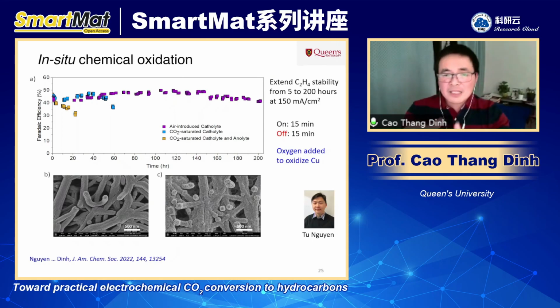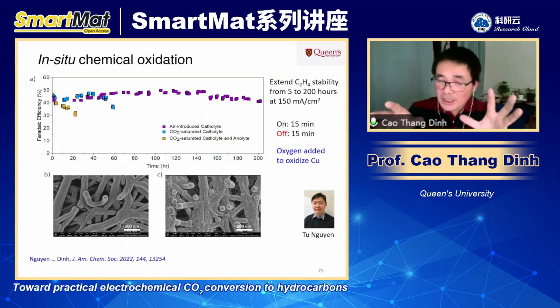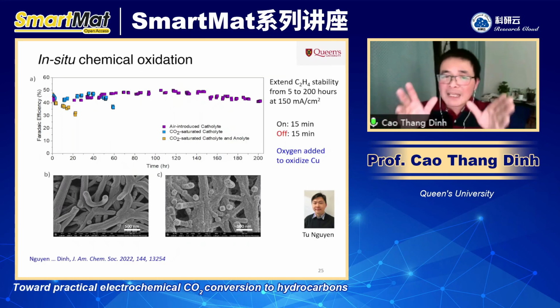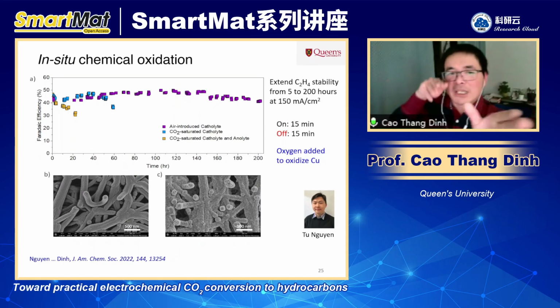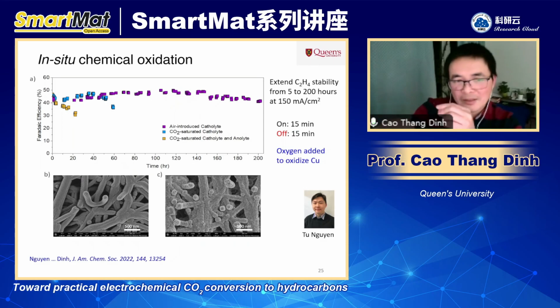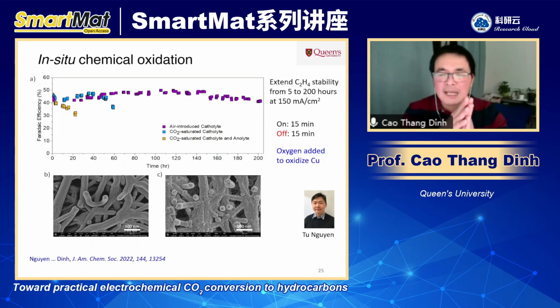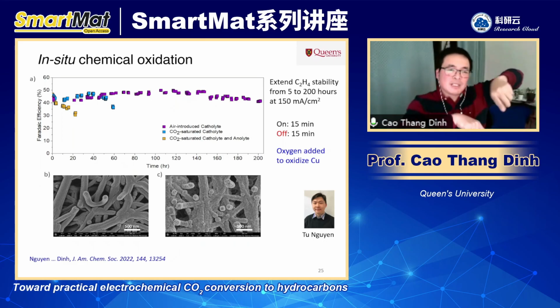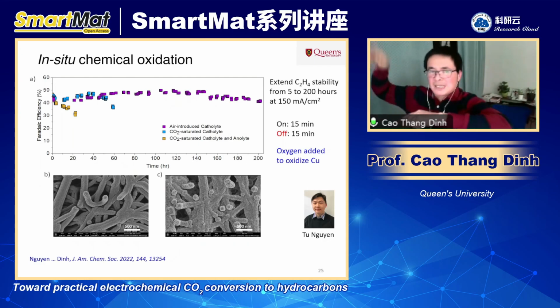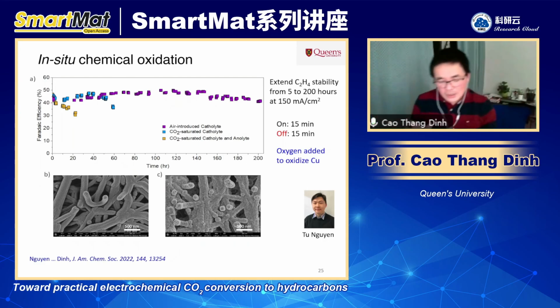So what we did in this work, with my postdoc visiting scientist, is that we use oxygen to oxidize the surface, right? We do not apply the positive current to oxidize the surface, but instead we turn off the system and introduce the oxygen to the cathode. So that oxygen is going to oxidize the surface of the copper, turn it into copper oxide. And then we run the reaction again after 15 minutes, right? So you run the reaction for 15 minutes, you turn it off for 15 minutes, and then you run it again. Just keep that cycle. And we try to understand what would be the role of oxygen in there.